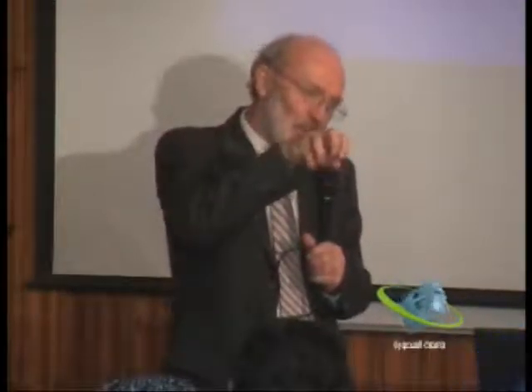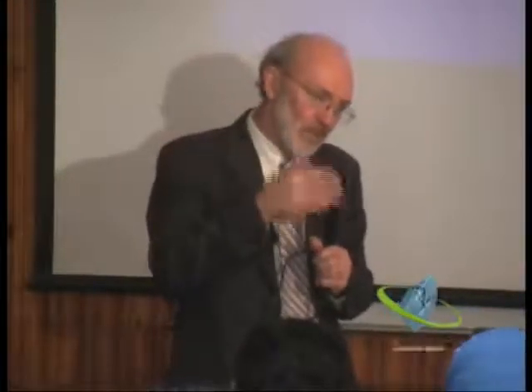Another former student of mine made spheres where they actually changed the CTE of the porcelain and changed that of the zirconia on the inside. They changed the diameter, and they found that the critical issue was rapid cooling. If they rapidly cooled, they got far, far more cracking and failure than if they slowly cooled those same systems. Even when the CTE was something like a 20-30% difference between the two, it was nowhere near as significant as the rapid cooling.